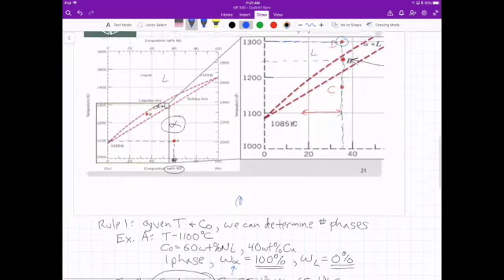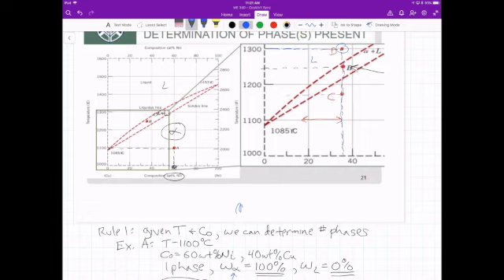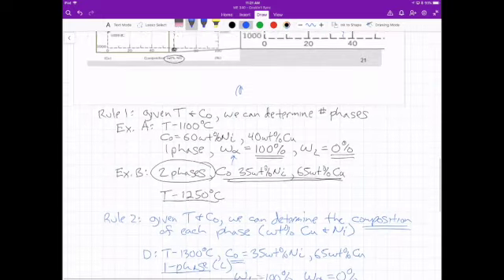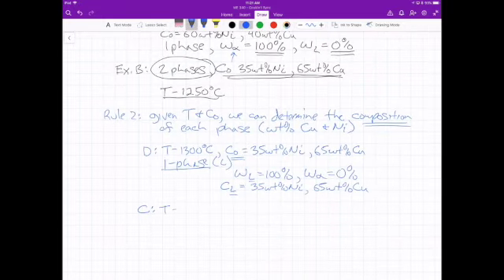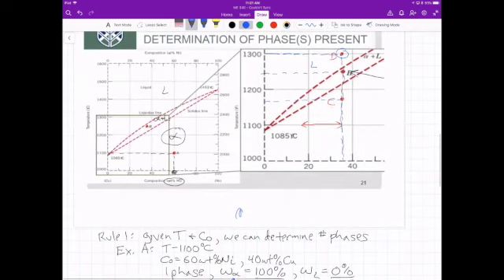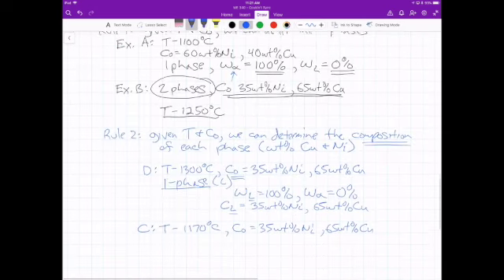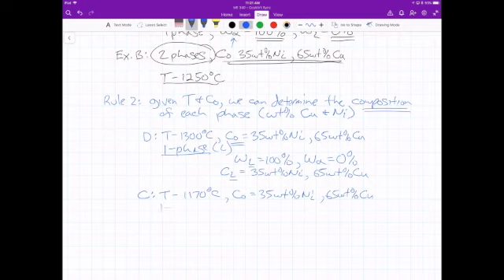for rule 2. Point C, we're down here now. Looks like we're at about 1160 degrees. Let's say 1170. So temperature is approximately 1170 degrees C. The initial concentration is still 35 weight percent nickel and 65 weight percent copper, right? How many phases exist? We're in the alpha phase. There's only one, so everything's solid. So we have one phase. That phase is alpha.